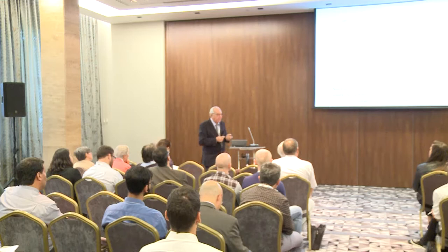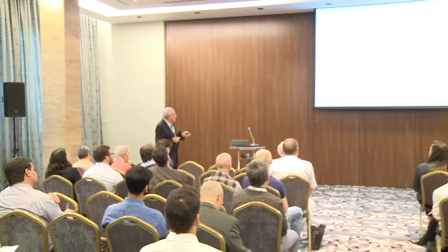Since energy is now a very important subject, people are revisiting this. I would also like to introduce what I call positive effects of hydrogen. Usually hydrogen is connected with negative effects, but we can also look at positive effects. For example, for titanium, the negative heat of solution is a beta-phase stabilizer. You heat to high temperature, cool down, and get a refined grain size, which leads to improved material properties — including increased fatigue life.